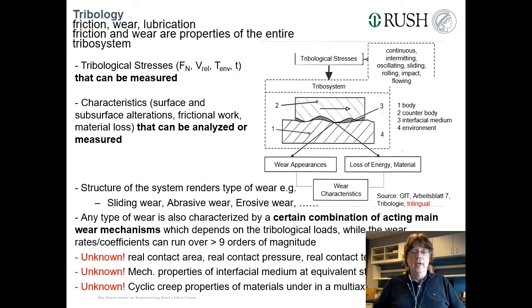What we know from the types of wear is that they are also characterized on the micro scale and sometimes on the nano scale by a certain combination of acting mechanisms and sub-mechanisms. And this is when the music comes in. Because what we really don't know is the real contact area or the real contact pressure. We don't know the mechanical properties of everything which is in between here, because it's sheared at mild and ultra-mild wear rates. This is what the industry is asking for. I will come to that point later on.